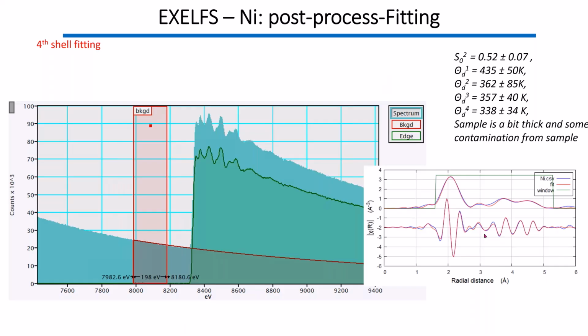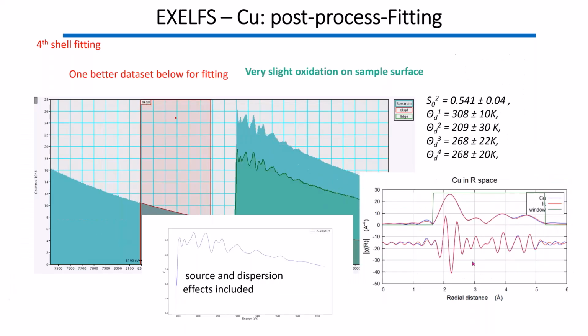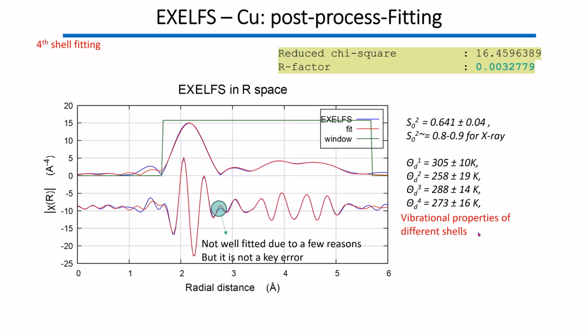Or maybe it's a good idea to do experiments closer to in situ, so that you can really see when the beam damage starts, and then you cut that slice off and exclude it from the analysis. Because in the end, you really care about the fitting quality. If you don't have a good fit, then whatever data it is, it's just data. So the final criterion is whether you can fit the radial distribution function properly or not. If you can't, it literally means the data has some issues.